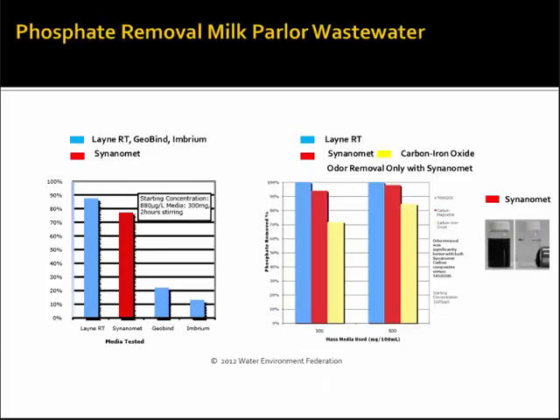So some testing of the Layne RT material, all beaker static mixed dose tests. I used milk parlor wastewater. It came in at about 14 ppm total phosphorus. We diluted it to 1 part per million to kind of equate to the national discharge standards.